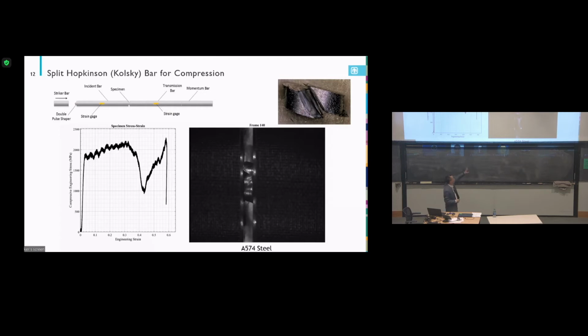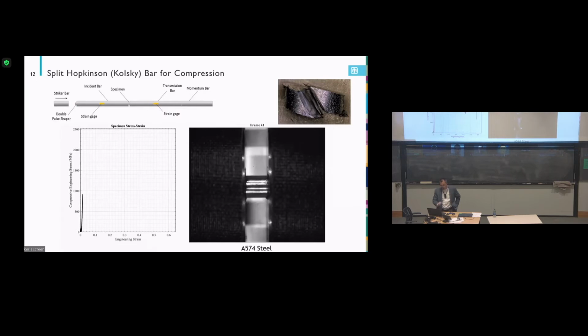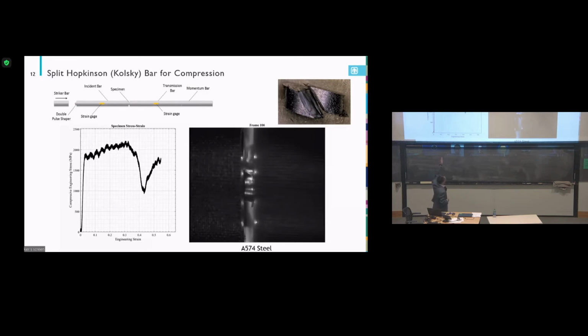But when you test different materials, you'll see different fracture behavior, and different stress-strain curves. So this is a steel. You can see it follows general linear elasticity, the yield, gets to plastic, then it drops, which means it got a shear fracture.